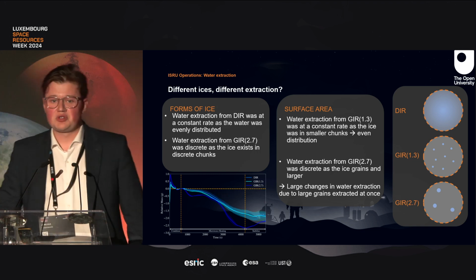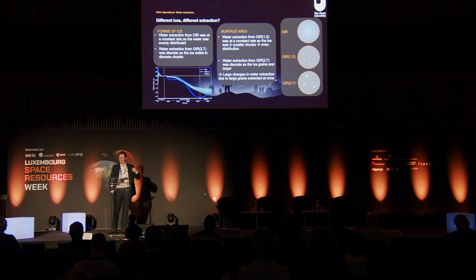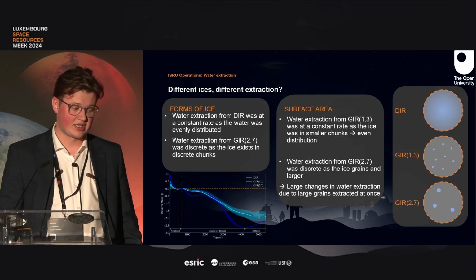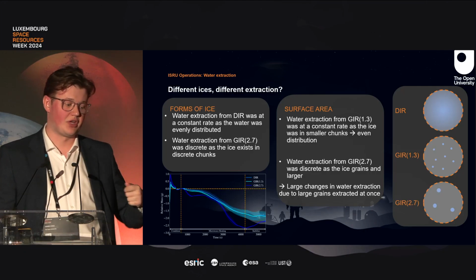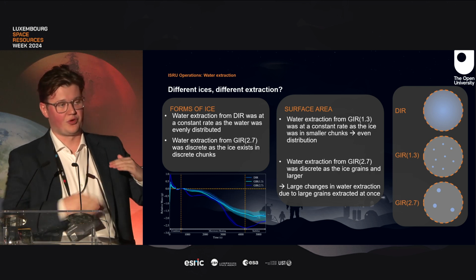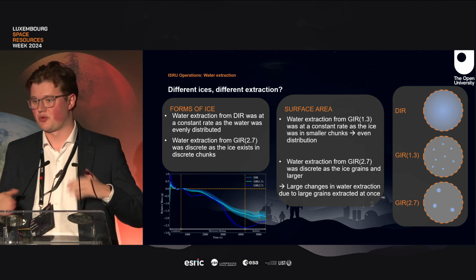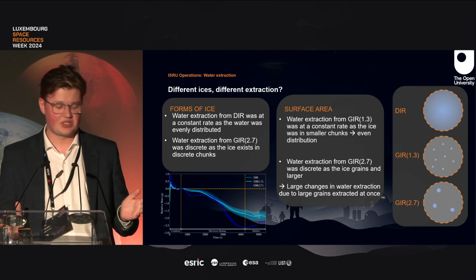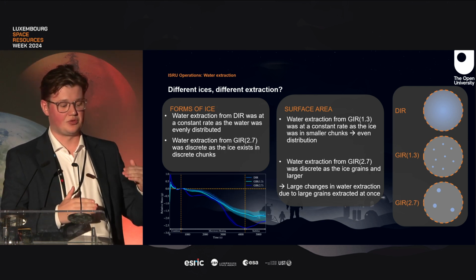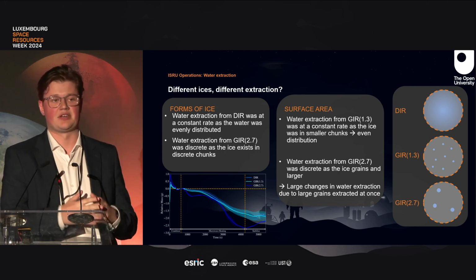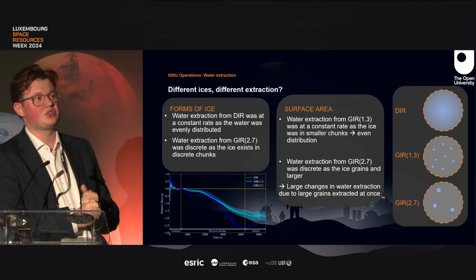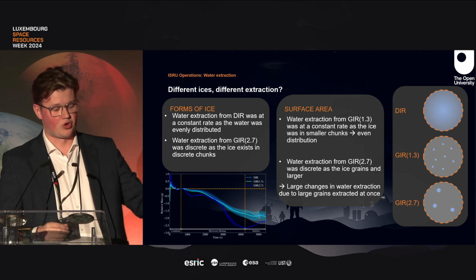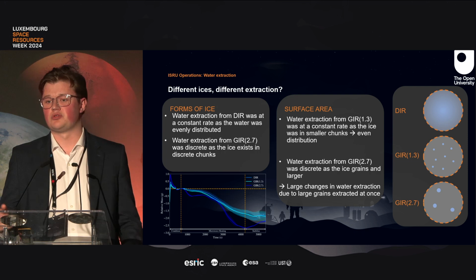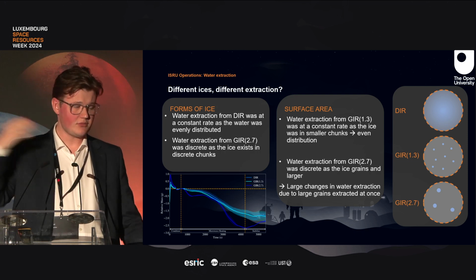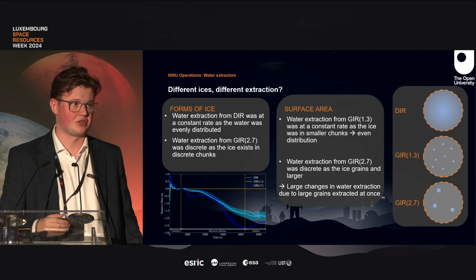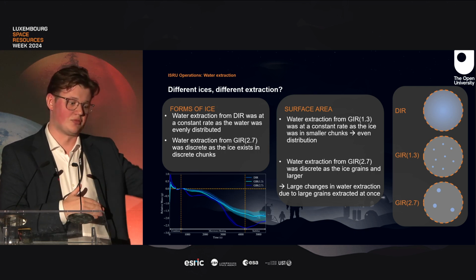So, as I said, the main thing I was looking into was what are the differences in extraction for the different forms of ice, and what we found was for the diffuse ice compared to the granular ice with the 1.3 millimeter grains, no real differences. But then if you compare it to the 2.7 millimeter grains, there is a big difference. And that can be quite easily explained. With the 2.7 millimeter grains, the first drop in mass that you see is probably the ice grains that lie on top of the sample, and then are extracted quite quickly when the microwave energy is turned on, because they're then also exposed to the vacuum of the system.